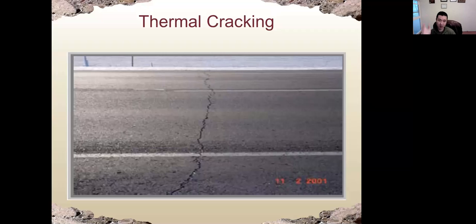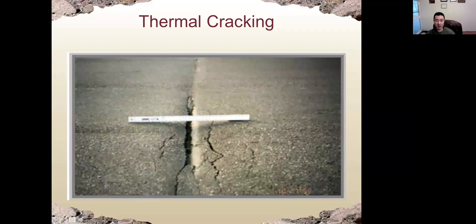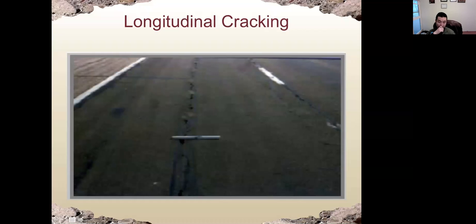The reason for that is because we have temperature change during winter or summer, and the viscosity of the asphalt binder is too high, or we have aging problems for the asphalt, which cause the viscosity to increase. So this is another picture of thermal cracking. Again, the crack direction will be perpendicular to the direction of the pavement. In this picture, the direction of the crack is parallel to the direction of the pavement. We call that longitudinal cracking. This is another type of fatigue cracking due to repeated loading.